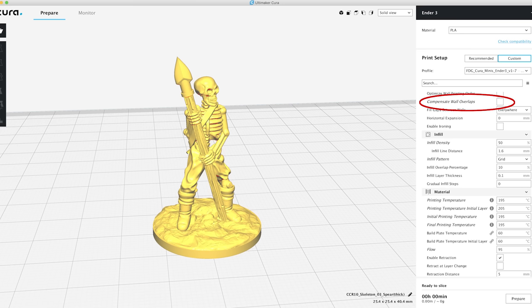If you're in Cura and you see the setting compensate wall overlaps, make sure this is off. This creates so many problems with surface quality that I've found. I've tried it with a number of different permutations with other settings in here, and I can never get it to produce. I understand the concept behind it, where you'd have two walls slightly overlapping. It reduces the extrusion on the second pass so that they don't overlap too much. But what I'm seeing is that the extrusion capabilities of most printers aren't fine enough that it can compensate fully for that. And you either start getting gaps where you don't want them. It just isn't worth it.